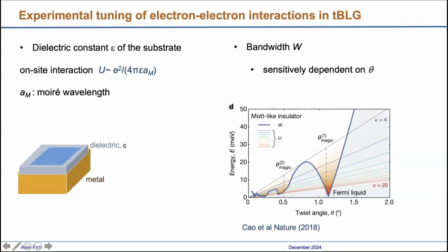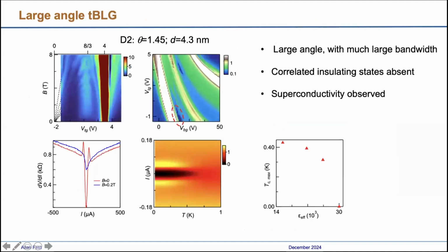Okay, so very briefly, we also have another sample that's a very large angle, which is 1.45 degrees, with a separation of about 4 nanometers. Interestingly, this is a really large angle, but we actually see a superconducting pocket here. This is definitely weaker superconductivity. TC is about 0.4 Kelvin, but we actually do see superconductivity here. It's also a little bit stronger here and a little weaker up here.